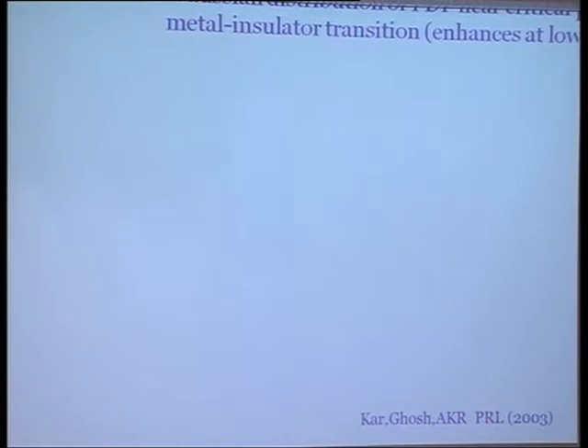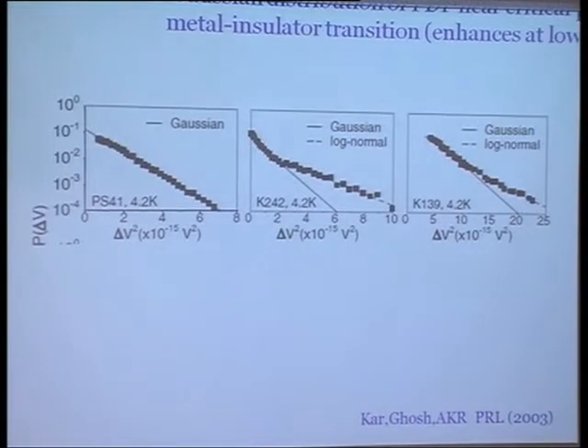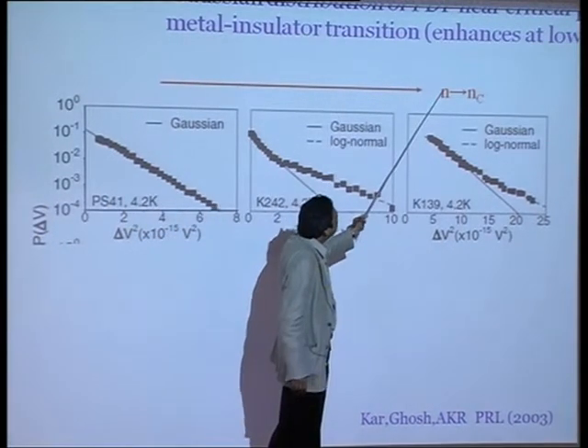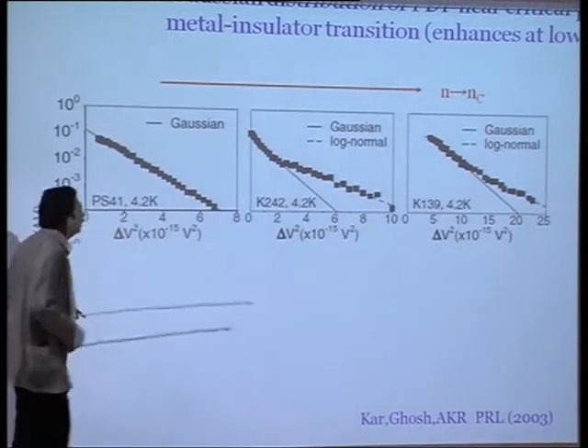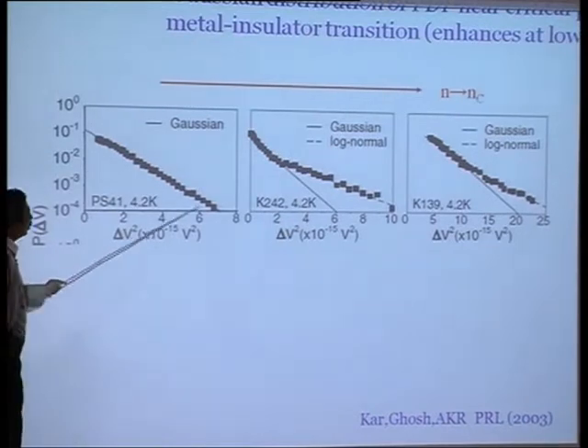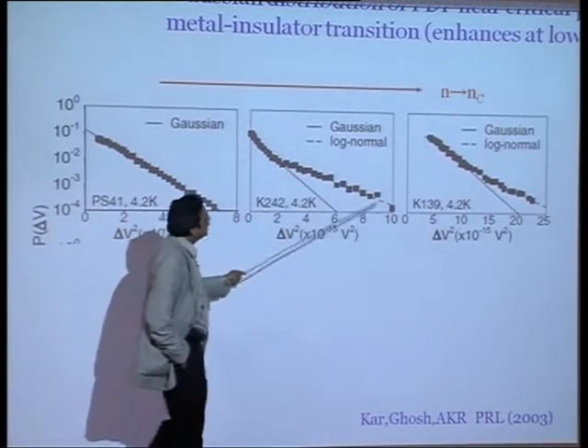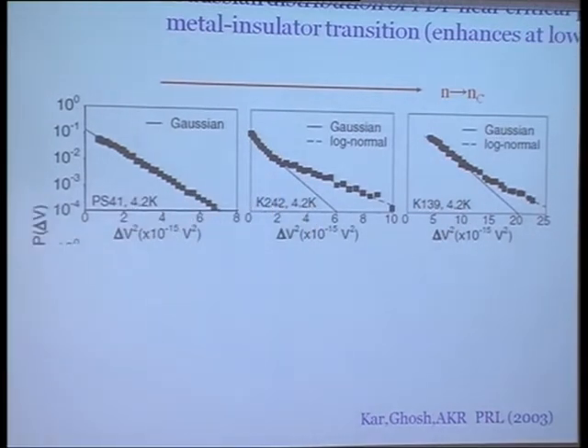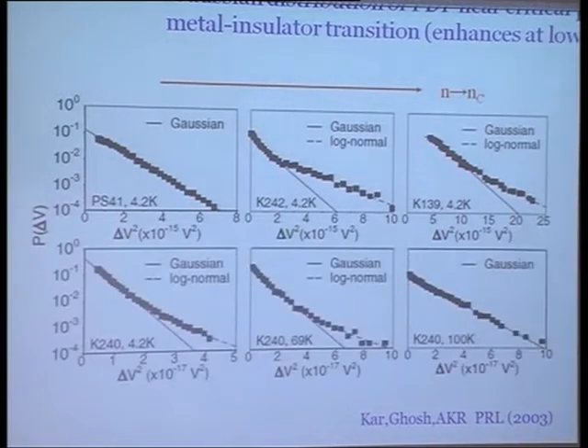The important point is that the non-Gaussian fluctuation not only gets enhanced as we approach the insulator metal transition, it also depends on the temperature. So let's see what happens here. As I am decreasing n, that is, as the density of electrons is coming closer to the critical region, you can see the fluctuation, which was Gaussian for more metallic samples, has started getting these long tails over here. This is a very clear signature that you are getting non-Gaussian fluctuation. And if you take the same sample that shows this tail at 4.2K and go to higher temperature, the tail again vanishes. It therefore depends on the time and the scale of relaxation and all those things.